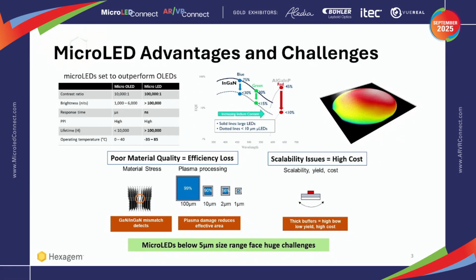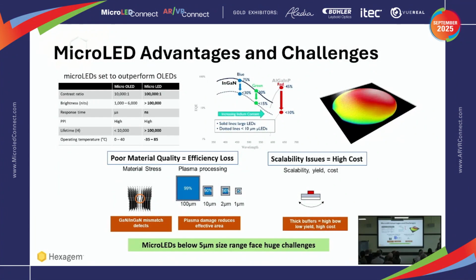The reason why, in particular for red, you have lower material quality is the lattice mismatch between GaN and the indium gallium nitride quantum wells. And of course, the higher the indium you have to use to reach red, the worse the problem. You create dislocations and other defects. Then in planar technologies, to make your LEDs, you use plasma processing, which induces damage on surfaces, but also in the material. And that becomes worse as you scale down, when the surface to volume ratio increases.